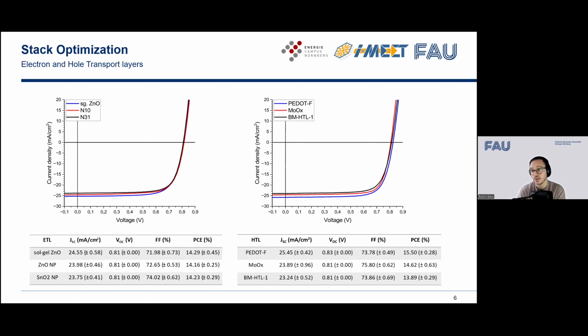But then, of course, we also have HTLs available that are solution processable, which in the end would be our goal. So we used PEDOT:PSS and BM-HTL1 and compared it to molybdenum oxide. And while BM-HTL1, for the same coating parameters as PEDOT:PSS, struggled a little bit, while still maintaining a high fill factor, but showed slight losses in JSC, with PEDOT:PSS we get really high current densities that are significantly higher than with molybdenum oxide. We get a quite high VOC in this specific experiment and with very high fill factors. And we ended up with 15.5% PCE on average for devices in this experiment. So hence we decided to use the sol gel as the ETL and PEDOT:PSS as the hole transport layer.